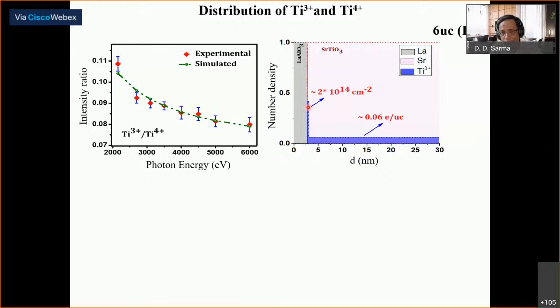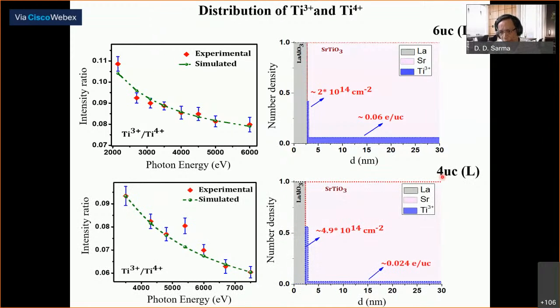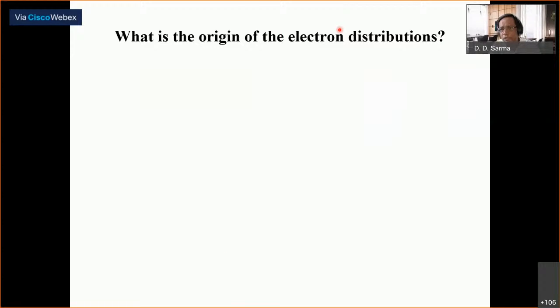And then I see that the distribution that is compatible, this green distribution, tells me that I need an electron distribution tied to the interface with a rather narrow width of a nanometer or less, with a density of 2 times 10 to the power 14 per square centimeter, which is the expected density that one would think from various considerations. But along with that, we find there's a very low electron density distributed, which can be evaluated in terms of per unit cell as a doping of about 0.06 electron per unit cell. And that also is critical to describe my experimental data. The same thing is true for the 4 UC sample, and I'll not belabor the point, but the numbers are similar and a similar description applies.